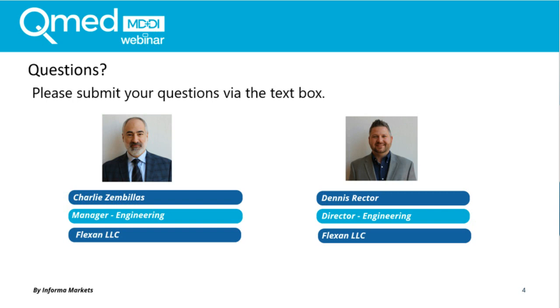That's done in an oven. And the third reason, if it's a peroxide cure silicone, as Charlie stated earlier, you want to drive off peroxide residuals, so that is also post-cured in an oven. The type of ovens that we use are convection ovens for all of our extrusions. All right, thank you, Dennis.